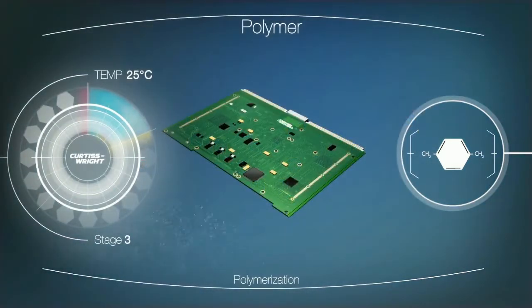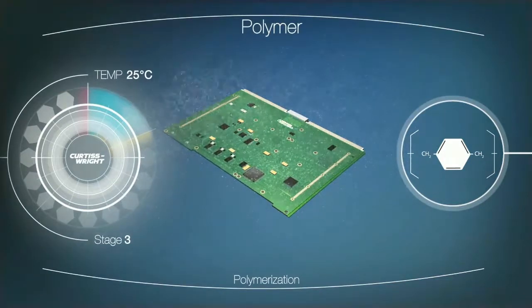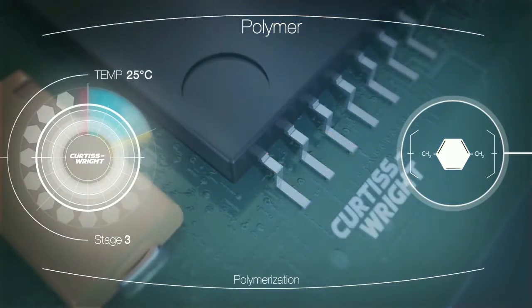At a rate of one to two microns per hour, a single clear coating builds up one molecule at a time, encapsulating all exposed surfaces. Controlled coating thicknesses ranging from less than 10 nanometers to 70 microns is achieved in a single operation.